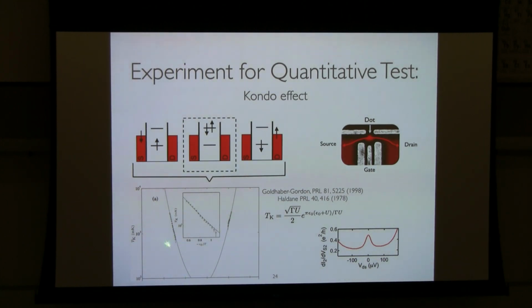And so what's captured in this plot is the result of a lot of analysis, but we extracted the Kondo temperature as we tuned the depth of the level below the Fermi level, and found that this is on a semi-log scale. This is depth of level, and here's a log scale for Kondo temperature, and indeed, it's falling exponentially. All right, it's not over a huge range because, unfortunately, my order for a zero temperature cryostat was perpetually delayed. But it's exponentially falling, and that was really quite exciting.